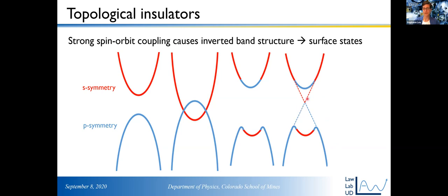These surface states form a Dirac cone and they are physically at the surface of the topological insulator. Wherever the topological insulator meets a normal material or a vacuum, which is a normal material, you get these surface states. If the topological insulator meets another topological insulator, you don't get any surface states because they're both inverted. There's nothing to unwind.